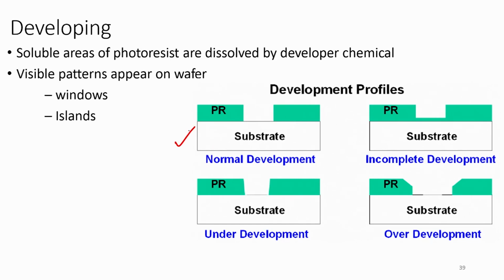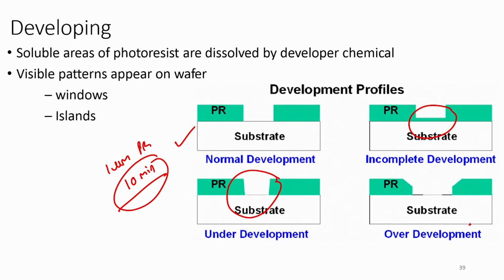However, if the time is less, say the developer time for developing 1 micron of photoresist is 10 minutes, and you take out the wafer before 10 minutes, then there can be incomplete development, which can also result in under development. While if you keep it for greater than 10 minutes, there will be over development. So all three cases, incomplete development, over development and under development, are not accepted. The recipe should be for 10 minutes and you should take out the substrate in 10 minutes.